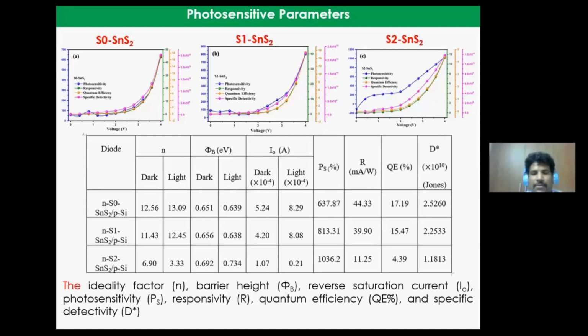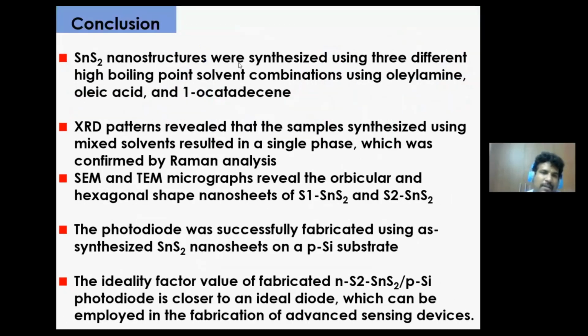So with this, I conclude our results. Tin disulfide nanostructures were synthesized using three different high boiling point solvent combinations using oleylamine, oleic acid, and octadecene, and XRD patterns reveal that the samples synthesized using mixed solvents result in a single phase. Both mixed solvents, using all three, and oleylamine with oleic acid show a single phase. Only oleylamine leads to multi-phase. So multi-phase can be controlled using oleic acid and octadecene.